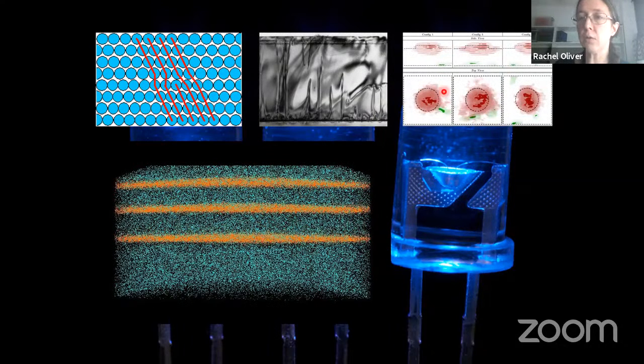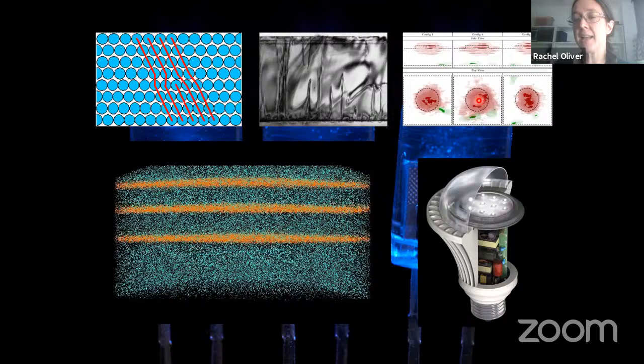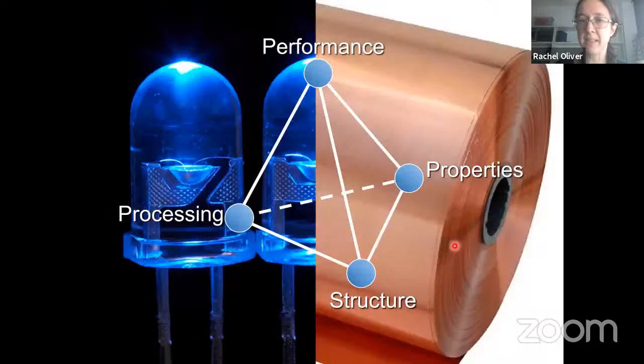Nonetheless, because of the effects of the random localization centers which appear just because sometimes you do get a few indium atoms at random close together, and because of other microstructure, the thickness fluctuations in the quantum wells, we do see strong localization of both the electron and the hole. And that is what is enabling these highly defected materials to be successful performers in the LED light bulbs, which are revolutionizing lighting and making it much, much more environmentally friendly.